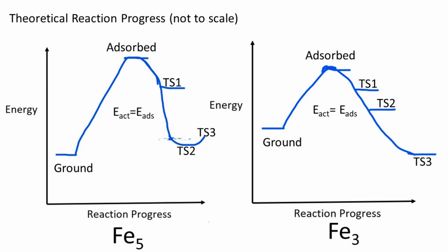In a future study, the addition of more and larger oil molecules will provide better insight into the possibility of cross-polymerization. There are two main takeaways here. One, if the large energy barrier to adsorption is overcome, then it is energetically favorable for an iron molecule to abstract a hydrogen. This means that contact of the oil with the bare iron surface may be enough to form a carbon radical. More importantly, depending on the adsorption site, the carbon radical may either participate in a polymerization reaction or attach to the iron surface.